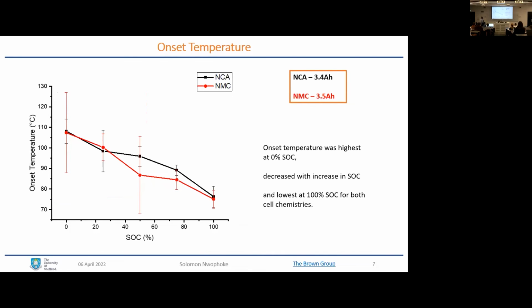Then the onset temperature for the test, each at a different state of charge. The test was repeated 4 times to observe the difference, how the onset varies with cells. So that's why I have the error bar showing the variation across the batteries. The red plot represents the NMC, and the highest onset temperature was recorded at 0. That means it is most stable at that point. The battery takes longer, endures more heat before undergoing thermal runaway, and that decreased with increase in state of charge to record the lowest at 100% state of charge.